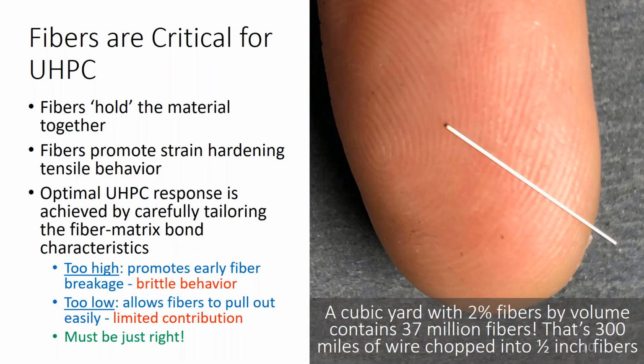But in order to get these benefits, you have to ensure optimal bond between the fiber and the surrounding matrix. If the bond is too high, the fiber will just break, and all you have done is just wasted the fiber. You've just increased the strength slightly, but no ductility. If the bond is too low, the fibers will pull out, and again, limited contribution. So it has to be just right. And if you get that correct, then that's when you have UHPC.